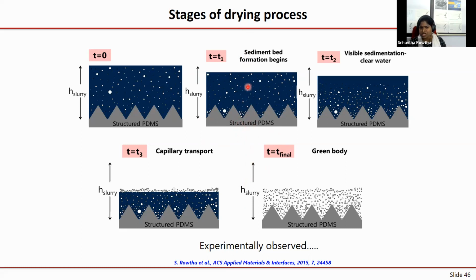Okay. Now, apart from this removal of water, there is definitely some sedimentation happening. One could model it by Stokes' law, and there is also some Brownian motion, but our particles are not that small, so we can neglect the Brownian motion. So typically, we can see some sedimentation happening. After a while, I have even observed experimentally that there is clear water present on the top. Just like, you take some muddy water, pour it in a beaker and wait for a while. On the top, you will be able to see clear water, right? So it's the same thing I have seen.